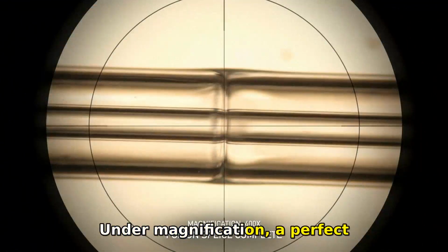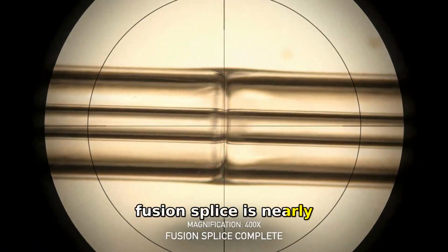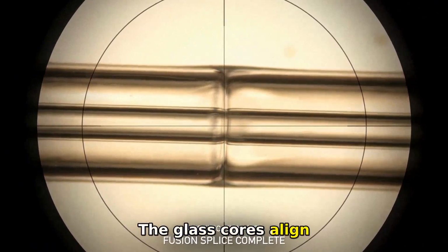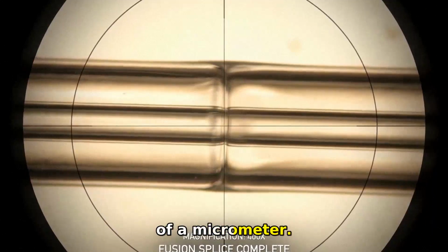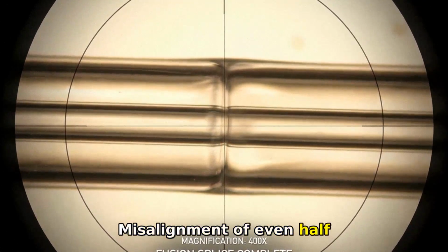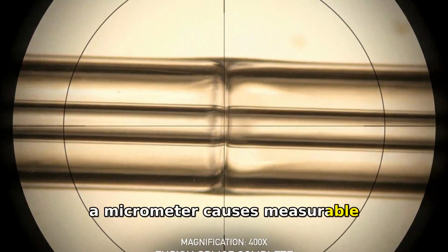Under magnification, a perfect fusion splice is nearly invisible. The glass cores align to within a fraction of a micrometer. Misalignment of even half a micrometer causes measurable signal loss.